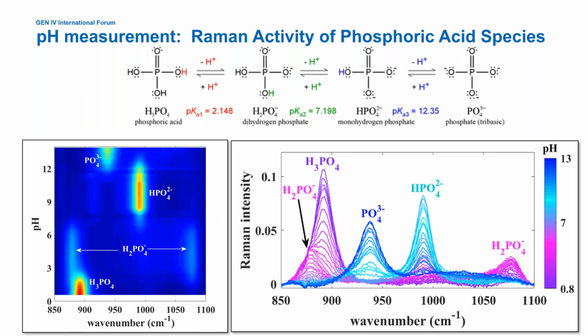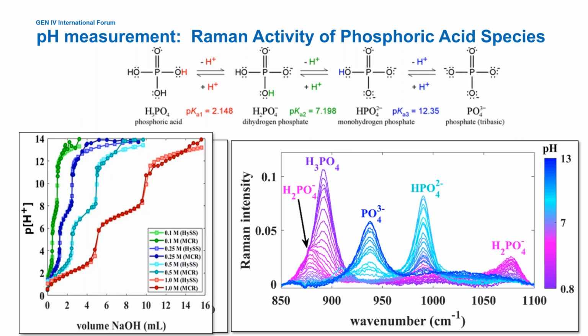We know the spectra at each pH. We know the concentration. We can form a chemometric model. And when we plot the measured pH from our chemometric Raman model as a function of titration, we can overlay that. I'm going to just point out we have several titration curves here at variable concentration of phosphoric acid. I'm going to focus on this red curve here, which is 1 molar phosphoric acid.